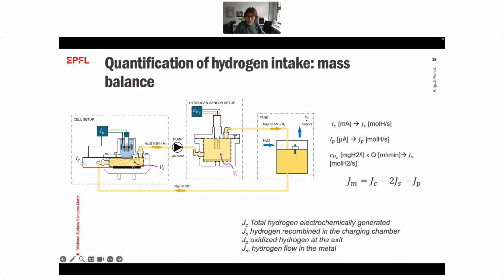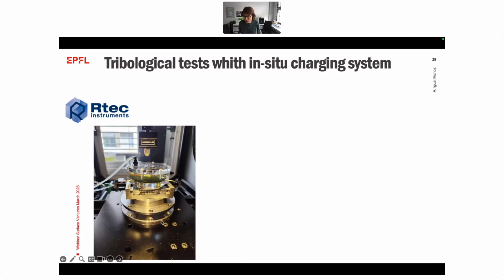This system can be a little bit more elaborate to determine exactly how much hydrogen is trapped in the steel, because then we do just a mass balance. I know the amount of current I use to reduce the proton. This proton will partly enter into the steel, and partly be recombined, forming hydrogen. If I have a hydrogen sensor in the solution, and I know the amount of hydrogen that has been recombined, I can determine how much has gone through. In the exit part, I determine this diffused hydrogen. The difference is what remains in the steel. This is another way to determine the amount of trapped hydrogen in the steel. So this is with respect to the generation of the hydrogen flow, and then the quantification of this flow.